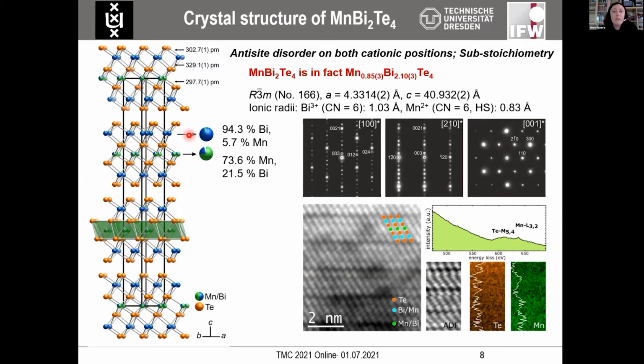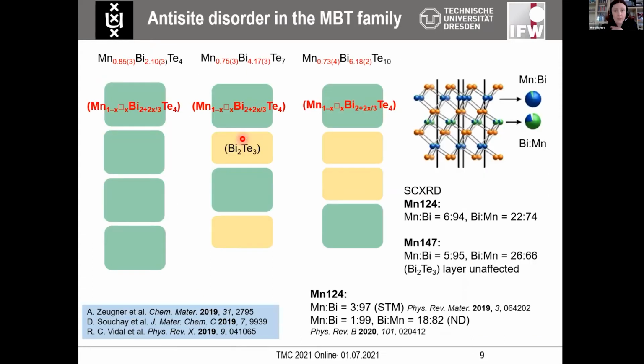Surprisingly, when we tried to synthesize further crystals of this type by varying the conditions, we would always end up with more or less the same intermixing pattern for 1-2-4 with bismuth. So it can be argued that it is somehow kinetics controlled. We are limited, of course, by this very narrow temperature range where we synthesize the crystals, but it could also have some underlying electronic or structural effects that we are not aware of. Despite all the efforts, we could not find any additional superstructure ordering, so this disorder is truly statistical.